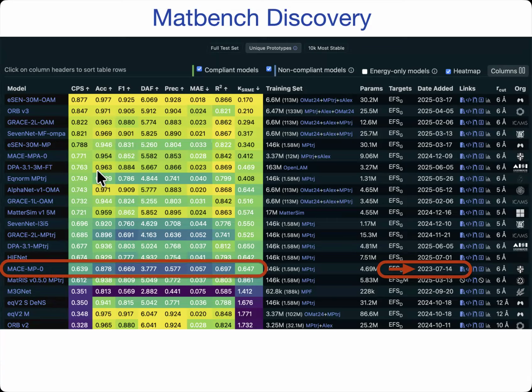So the test here, and much of these correlated metrics, these are the F1 score, the precision, the MAE, the R-squared, they're all about trying to predict the stability of a new material on the convex hull. And when MACE was first fitted, it gave a real jump in performance. So if you look at, again, the dates, the 2022 M3GNet was the previous best model.